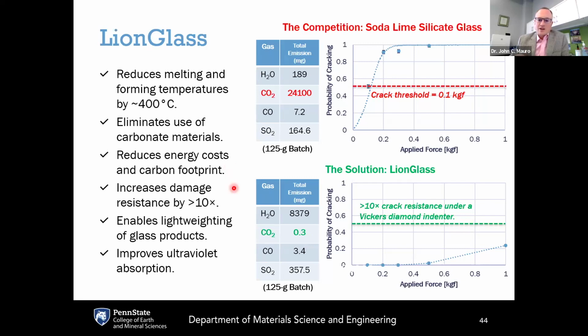Another nice thing about LionGlass is its improved mechanical performance compared to soda-lime silicate. The upper right plot shows the probability of soda-lime silicate glass cracking under an applied force, under a Vickers diamond indenter.